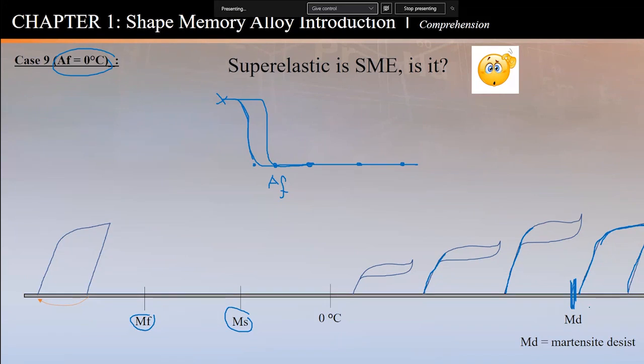But the takeaway from this message is most SMAs can show superelasticity above AF and martensite shape memory effect below MF. In other words, if I have a structure and it requires a superelastic alloy, I need to do something for that alloy so that AF is below what I needed to use. If I need to use this as an actuator, I need to operate between MF and AF. So if I operate here, I have an actuator. If I operate here, I have superelasticity. And it's really the same material.